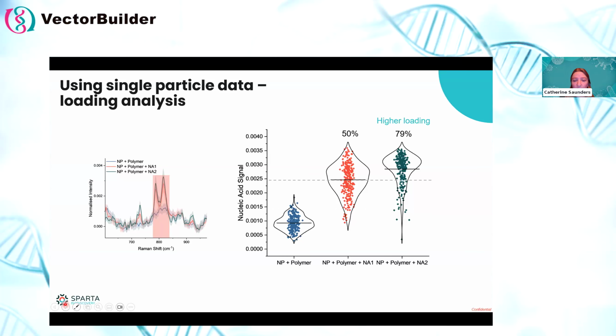I can also change the position of this threshold to look at the average amount of one loading condition compared to another one. So this is a 50% threshold on the Na1 condition. And what you can see is that actually 79% of the Na2 particles have a higher signal. So this Na2 condition led to more particles with more loading. So we'd say this is the higher loaded, the optimal condition.